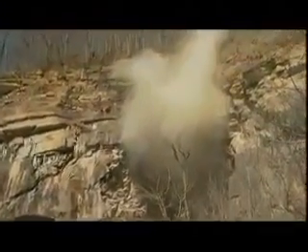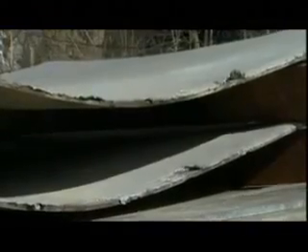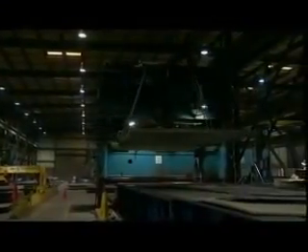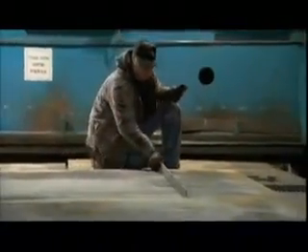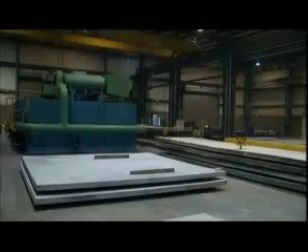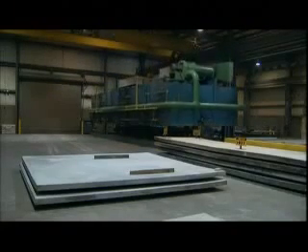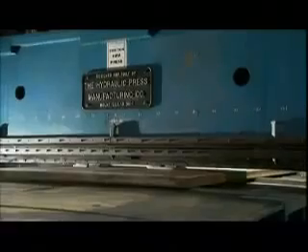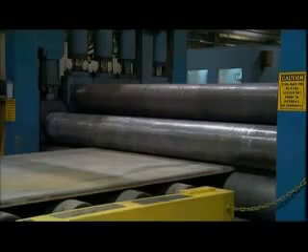Because of the intense dust created by the explosion, workers can't retrieve the newly formed clad from the explosion chamber for more than 18 hours. Not surprisingly, the power of the explosion can cause significant deformation to the newly formed clad. Therefore, upon its return to DMC's central processing facility, the clad undergoes a final series of corrections. These include heating the clad in an oven that causes the metals to soften slightly. This relieves stress from the blunt force of the explosion's impact. Any bowing or misshapen curves are flattened out by either a 3 million pound press or, for thinner clad, by a series of rollers known as levelers.